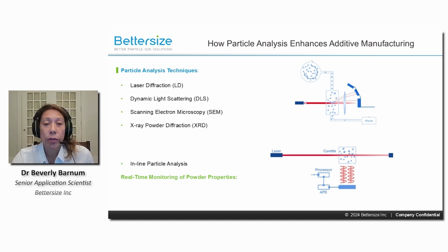But the cons are that the math involved for laser diffraction assumes that the particles are spherical. Dynamic light scattering is often used for smaller particle ranges in the nanoscale. This ensures the consistency of the microstructure of the formed parts. Particle size range here is less than a nanometer to about 15 microns. And the pros are this provides hydrodynamic size and is good for small particles and colloids. Again, the cons are that the math assumes particles to be spherical and that this process is also affected by sample preparation.